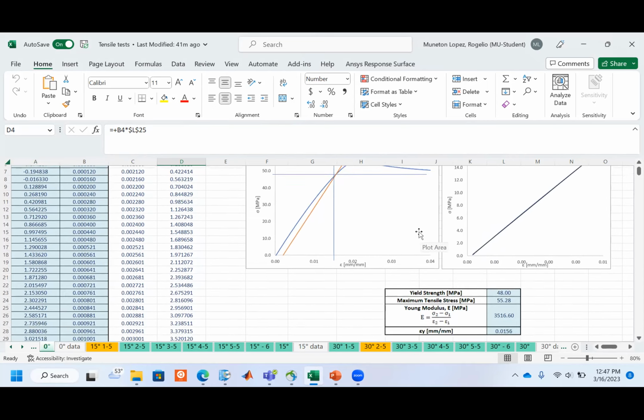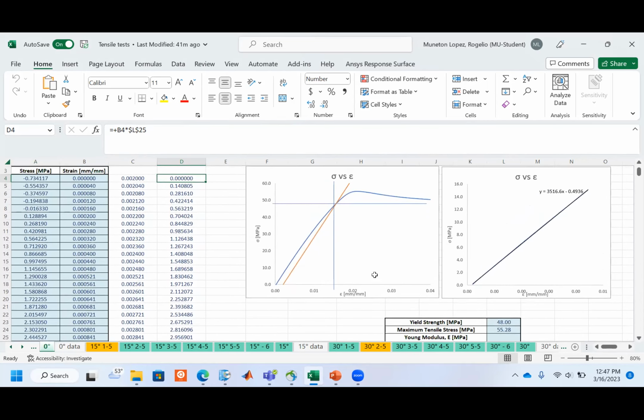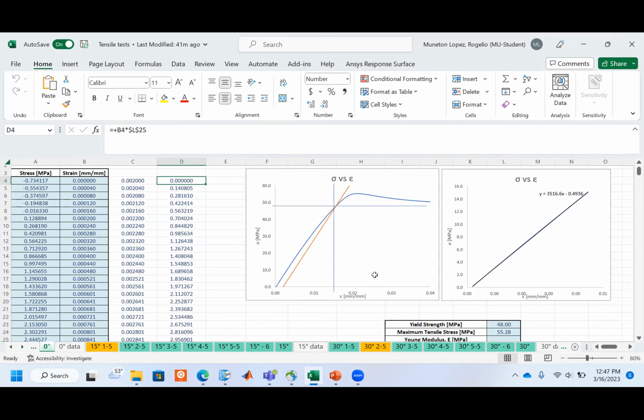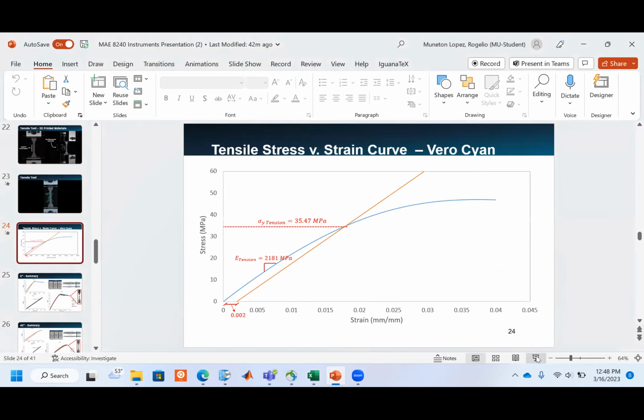To obtain the yield strength, I'm using the 0.2% strain criteria, which consists of plotting a line parallel to the first portion of this curve with that 0.002 offset strain. So the point where the line and the stress versus strain curve intersect corresponds to the yield strength. In this way, we can process the data and obtain these two material properties for this type of material, or for whatever material.